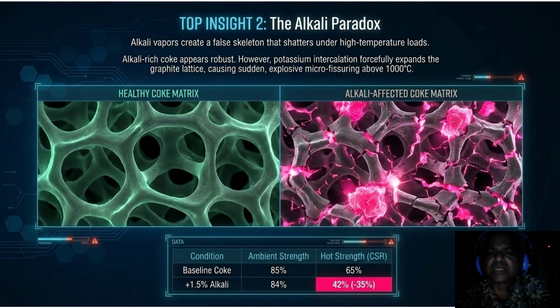Look at the data table. At ambient strength, the alkali coke is nearly identical to baseline at 84%. But look at the hot strength, or the CSR. The baseline stays at 65%, while the alkali affected coke drops to 42%, a 35% drop. So operationally, this means your strong coke becomes dust exactly where you need it to be a spacer.